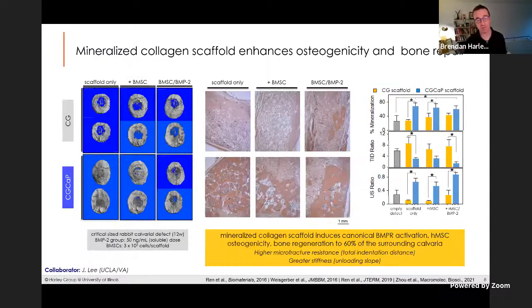And so this is a model from a rabbit where we take non-mineralized scaffolds and we see largely just soft tissue that forms in the defect. So this is a defect in the skull of a rabbit. It's known as a critical size defect, meaning if we do nothing to it, it won't heal. And you see largely these non-mineralized scaffolds on the top, like over here on the left. You see very little new bone formation in these blue regions in the middle, which is where the hole was. However, on our mineralized scaffolds, we see really efficient bone formation.